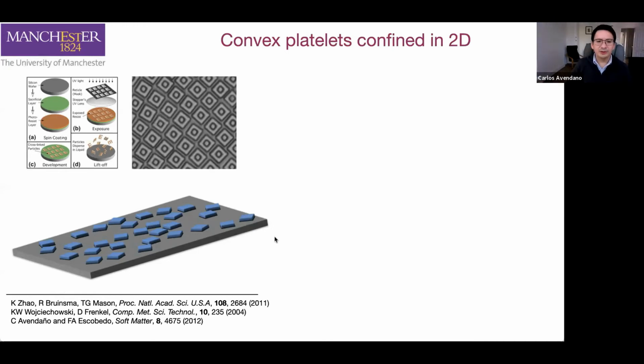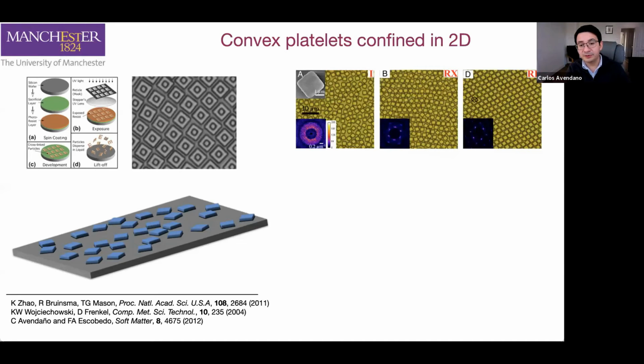Now, if we talk about square particles, the first thing that we will think is, okay, they should form square phases. That is what logic is telling us. If you have square objects at high densities, they should pack as simple squares. However, in the experiments, they didn't observe that. In the experiments, they observed the formation of 3 phases. At low density, at the top of this sample, they observed the formation of the isotropic phase. We can see that in the Fourier space, the density correlations form a ring, which is typically what you observe when you have an isotropic phase.